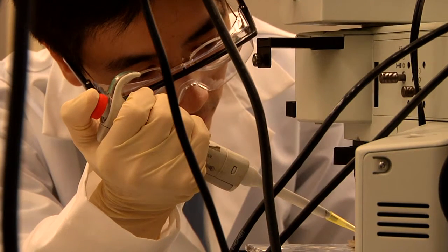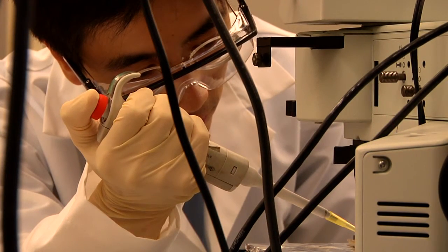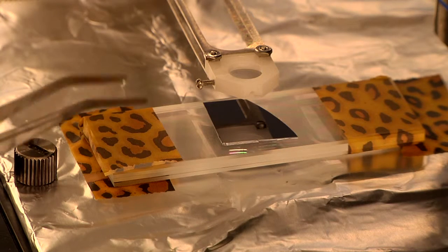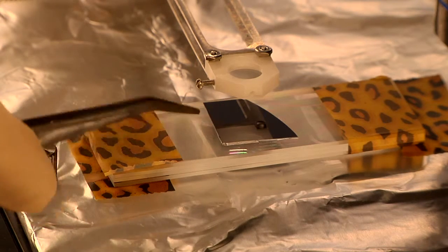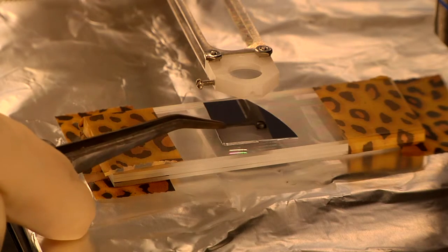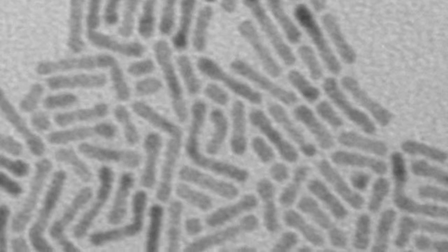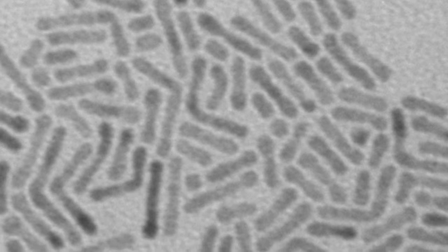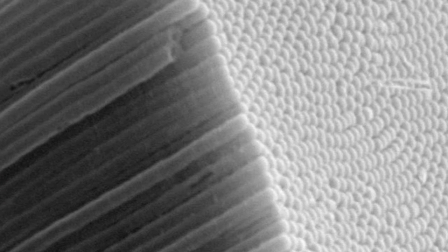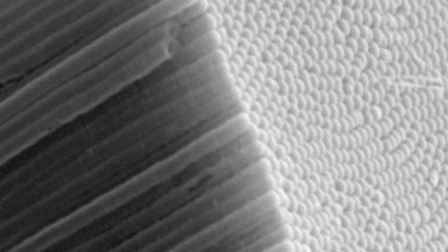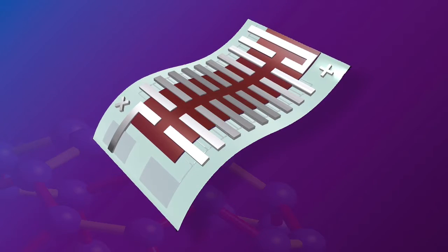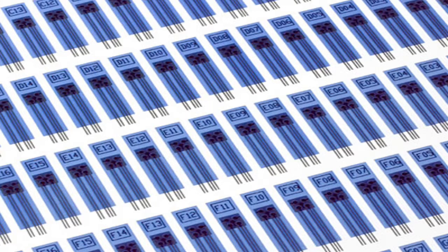By confining a drop of solution containing non-volatile solids between a curved upper surface and a flat substrate, then adjusting this geometry in microscopic increments, Lin discovered that the drying of the solution at the capillary edge created a series of concentric rings composed of the deposited solids. Those solids could be anything from polymers to nanocrystals to conductive polymer-based nanofibers, even DNA-based nanocomposites, whatever might be needed for applications in photonics, electronics, optoelectronics, biosensors, nanotechnology, and biotechnology, and at a fraction of the cost of other methods.